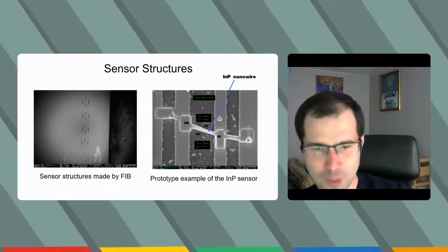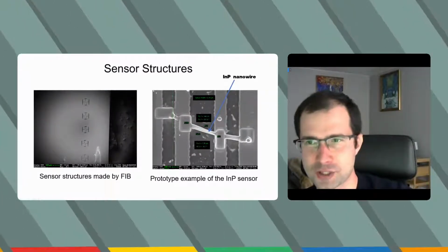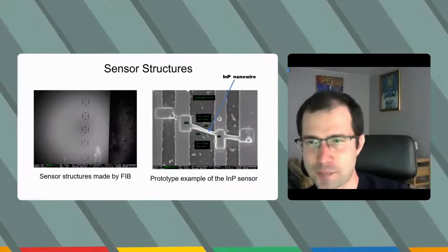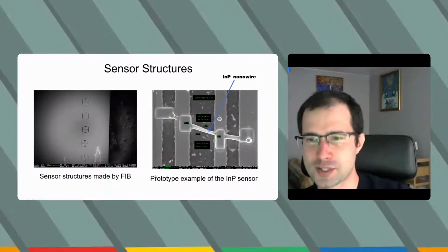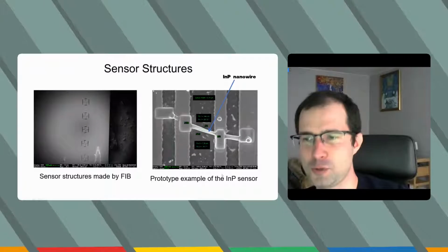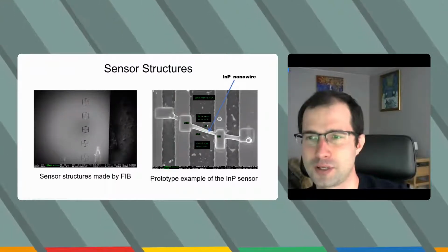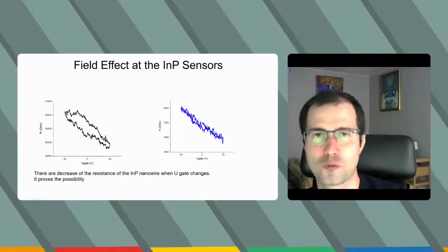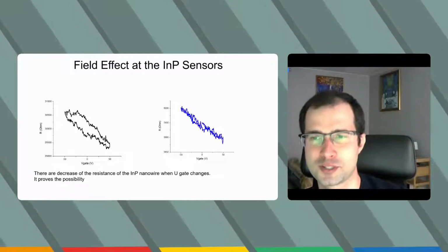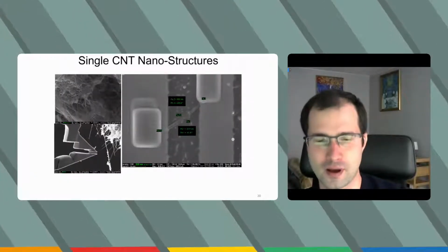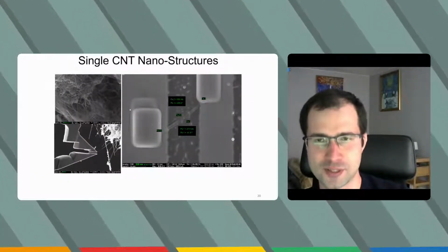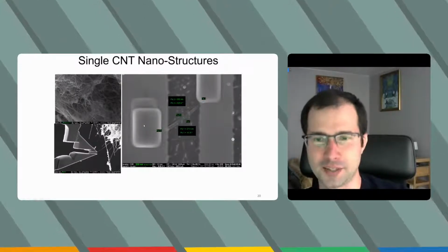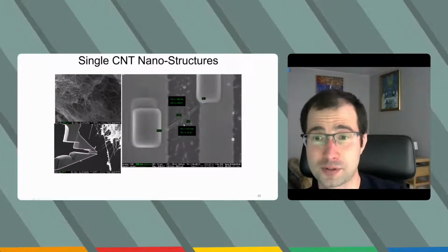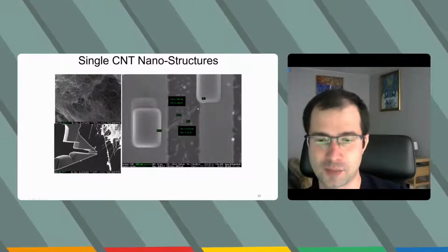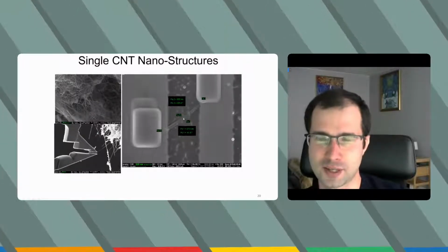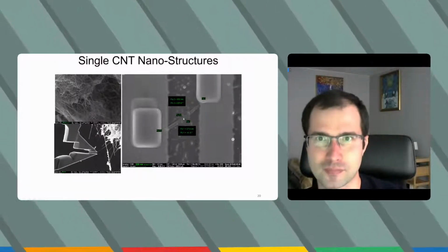So we can create such structures using shape memory effect composite nanotweezers. This is a prototype example of the indium phosphide biosensor. The field effect of the indium phosphide sensor will demonstrate it. Here you can see carbon nanotube nanostructures created by nanotweezers with a single carbon nanotube, thickness less than 30 nanometers.